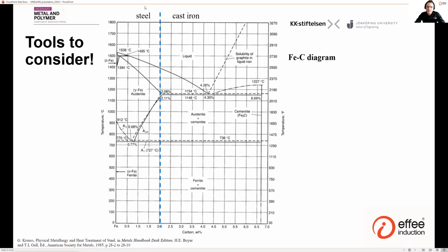On the y-axis, you have the temperature, and on the x-axis the carbon content. So I've divided with the blue line here the steel and the cast iron areas in general. There are mixes in between as well. For example, take a composition of 2.75% carbon, and we go from liquid and start to solidify this alloy. We will start solidifying at around 1330 degrees Celsius. In the diagram it's hard to see there, maybe, but it depends on the level of other alloying elements, of course.